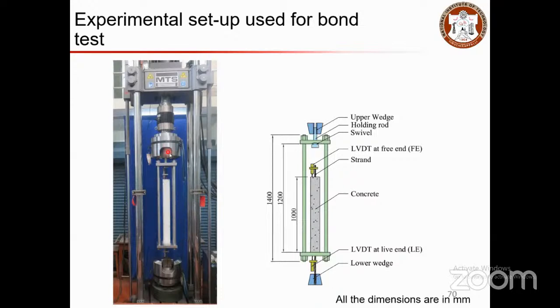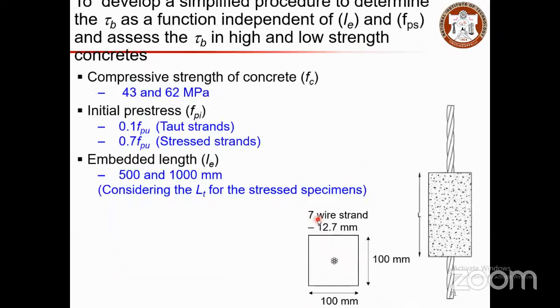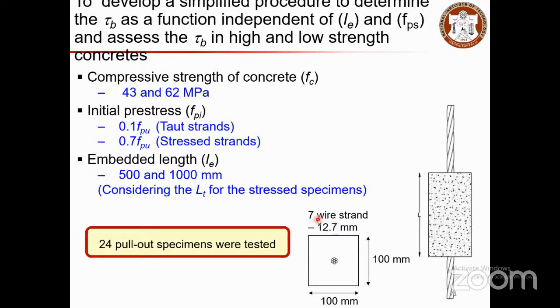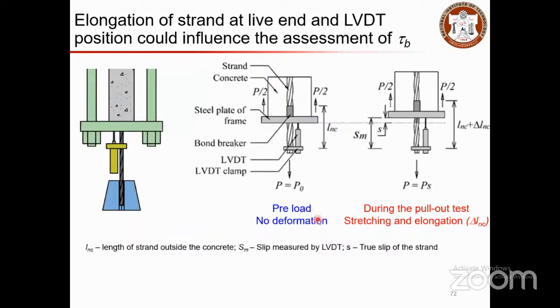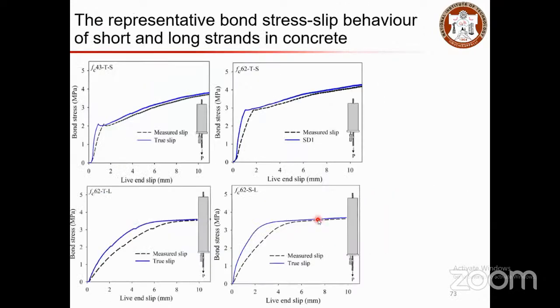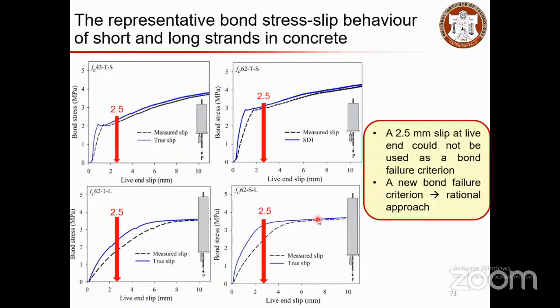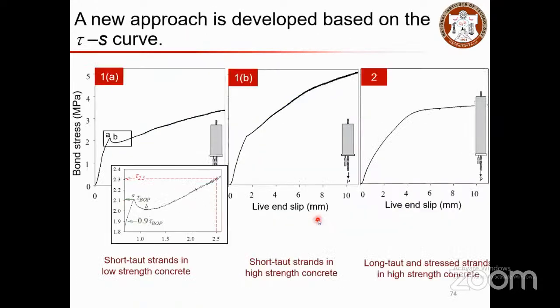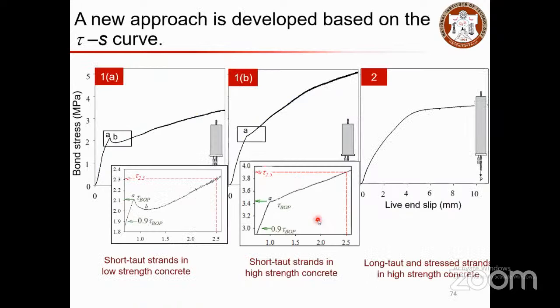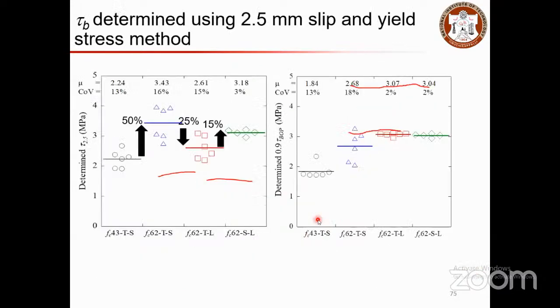This end is fixed, and then when it is being moved here, the strands are being pulled out from this end, and two measuring devices are placed at the ends to measure the slip at the ends of the members. Two different pre-stress levels and two different embedded lengths were considered. From the testing, we understood the behavior of the strands in concrete, and from the behavior, the failure criteria for the test methods were also come up with and proposed.